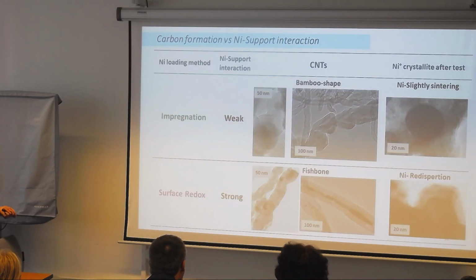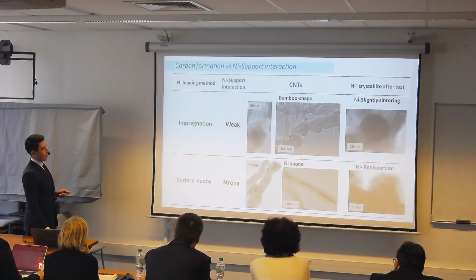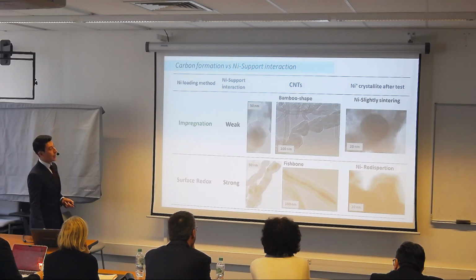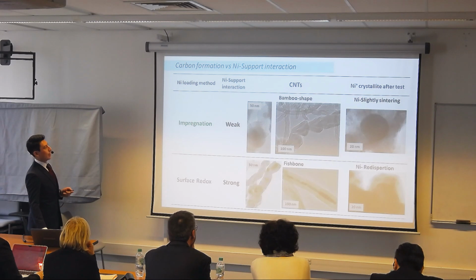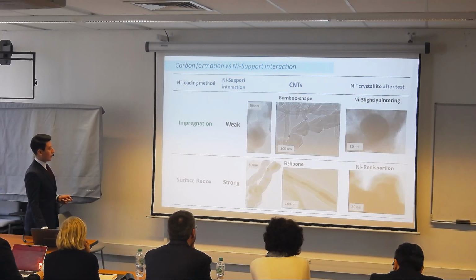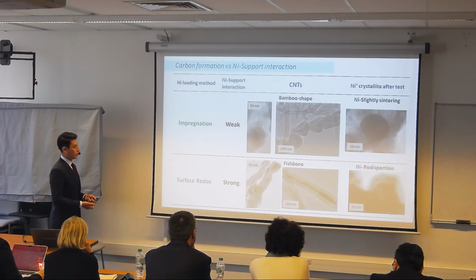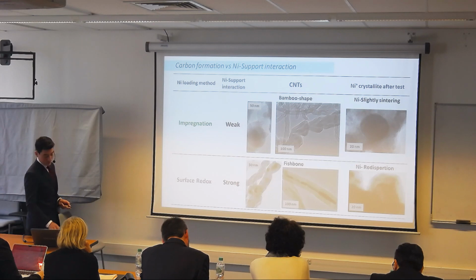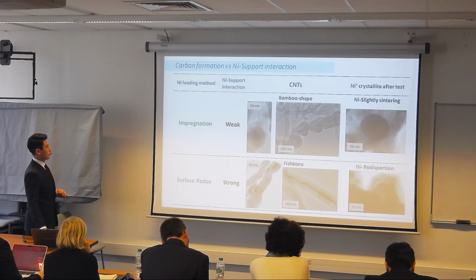I did a comparison between carbon formation and the nickel-support interaction. We can see here the two methods. With nickel by impregnation, we have a very weak interaction between these two phases, and we are also producing bamboo-shaped nanotubes, as I showed before, and that is also producing nickel sintering. However, in the surface redox method, we have a very strong interaction between these two phases, producing fishbone carbon nanotubes. And as I showed you in the table, we have a nickel redispersion.